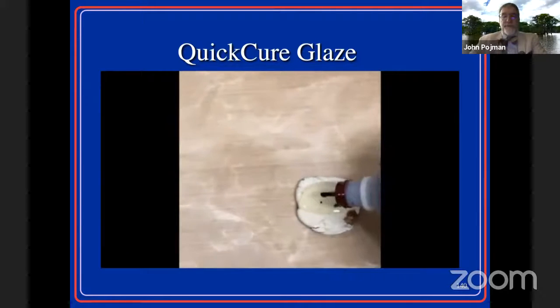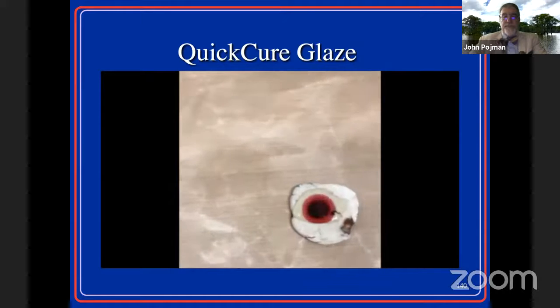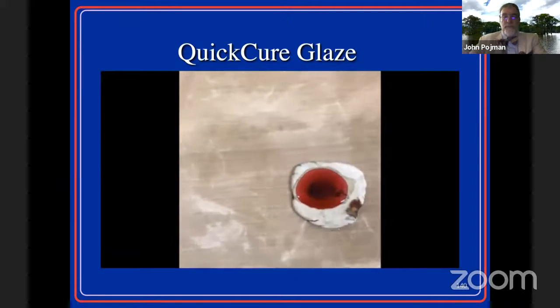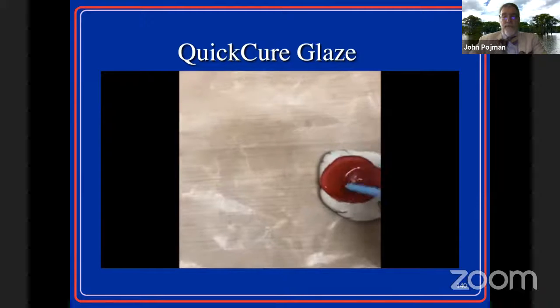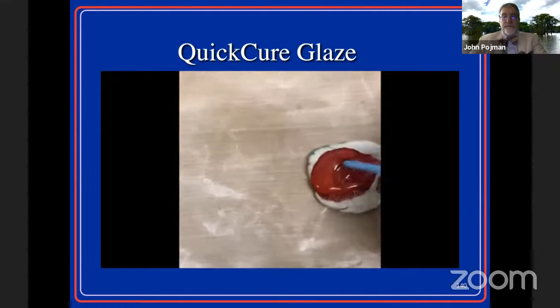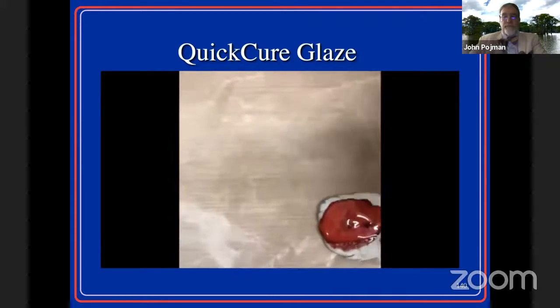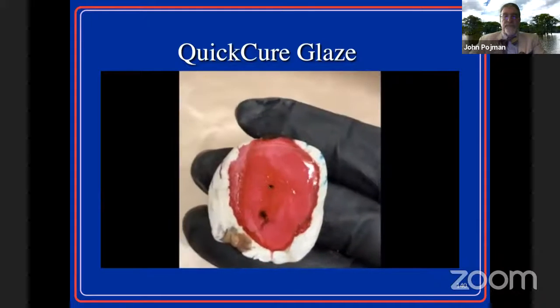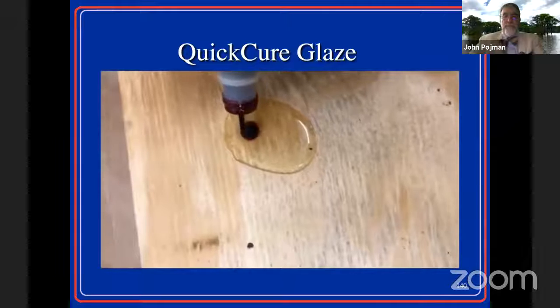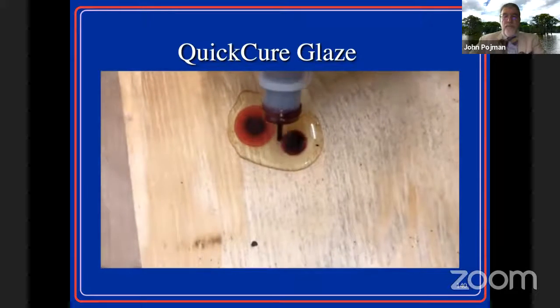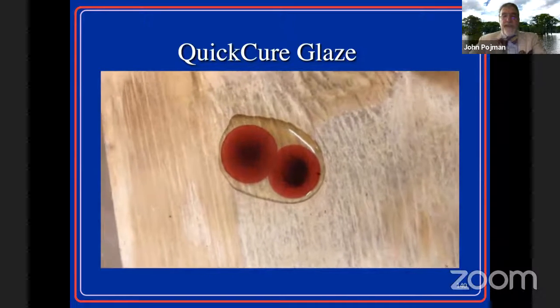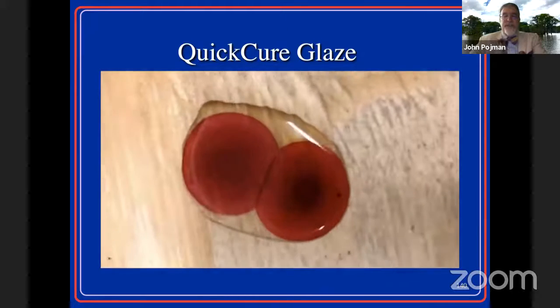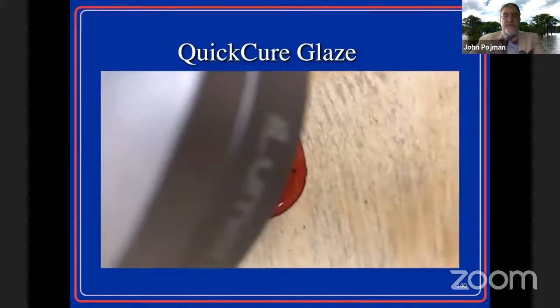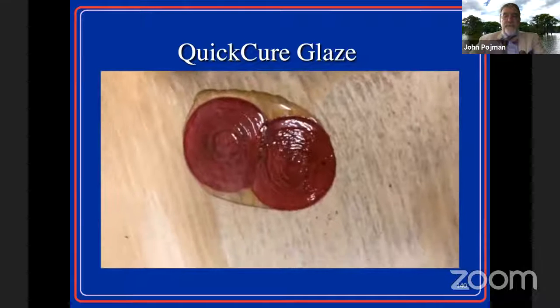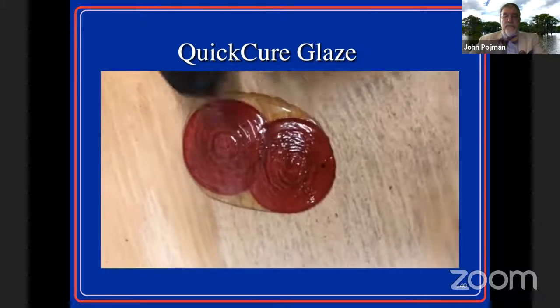Also possible to mix in alcohol inks. Again, cure for 20 seconds. Or you get some nice patterns formed, probably surface tension driven convection. We're able to create with Pojman Polymer Products a new quick cure glaze.